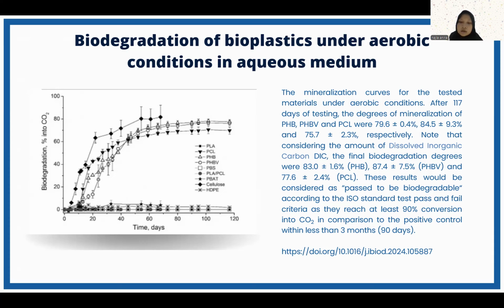Note that considering the amount of dissolved inorganic carbon or DIC, the final biodegradation degrees, where for PHB it is 83.0 plus minus 1.6%, and for PHBV is 87.4 plus minus 7.5%, and 77.6 plus minus 2.4% for PCL.